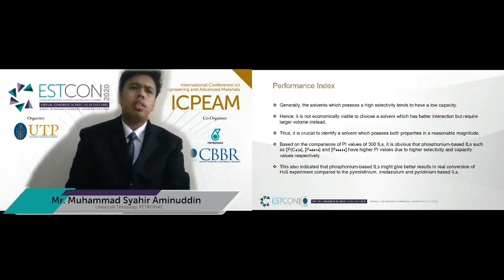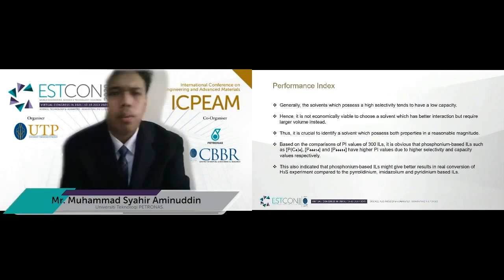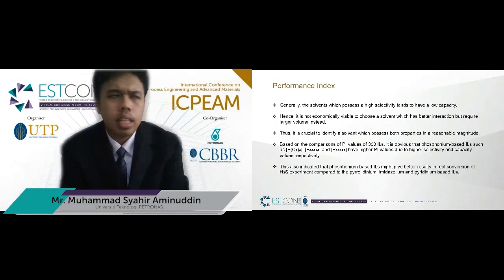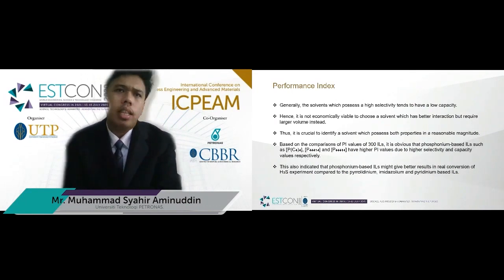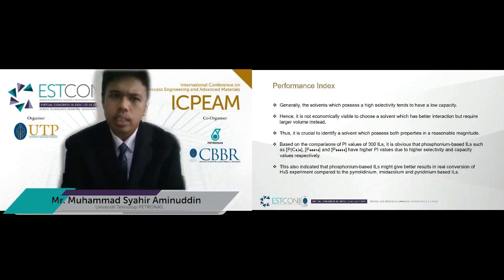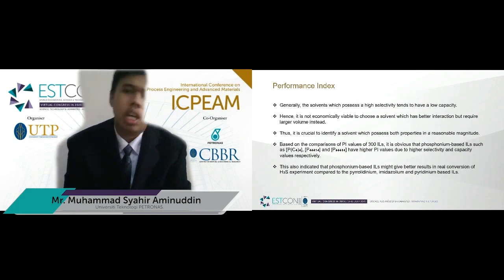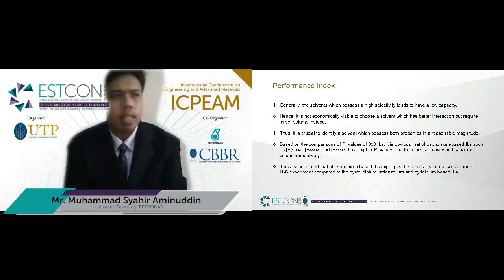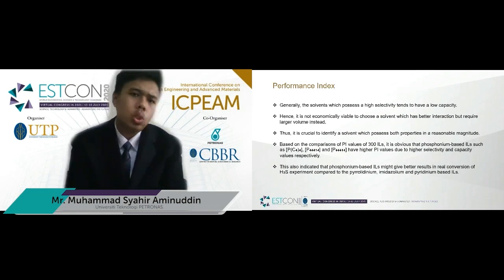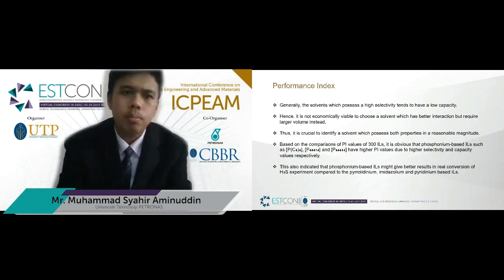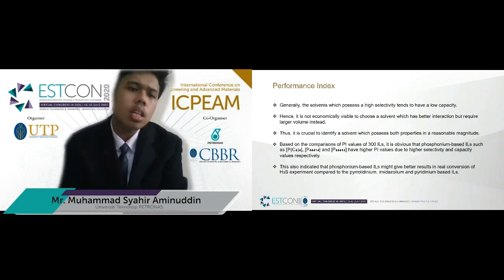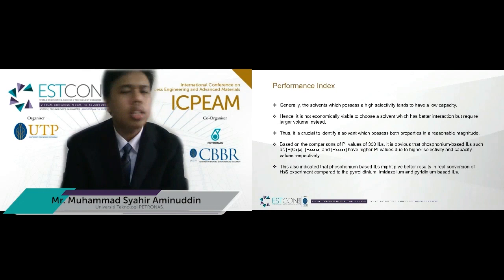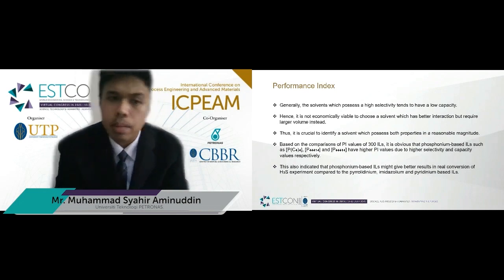Then we will proceed to the performance index. Performance index is used to evaluate the performance of the ionic liquids in conversion of H2S. Generally, a solvent which possesses a high selectivity tends to have a low capacity instead. Hence, it is not economically viable to choose a solvent which has better interaction but requires a larger volume. Thus, it is important to identify a solvent which possesses both properties in reasonable magnitude.